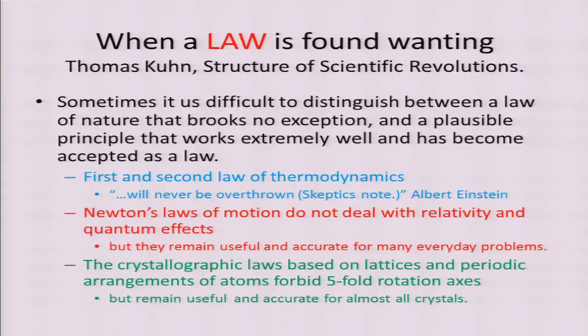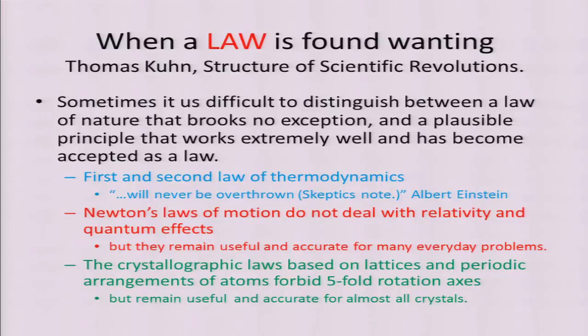Newton's law of motion does not deal with relativity and quantum effects, but it has a large range where it's valid. So even though we know that it isn't universally valid, we can say there is a range of properties, and we know exactly what they are. It's larger than a few atoms, and slower than some fraction of the velocity of light. So they remain useful and accurate for many everyday problems. The crystallographic laws, based on lattices and periodic arrangements of atoms, forbid 5-fold symmetry, but they remain useful and accurate for almost all crystals. You know immediately whether you have a crystal that has a lattice, and you know that the laws of crystallography must obey. So this wasn't really a very strong revolution, but this is what we published.